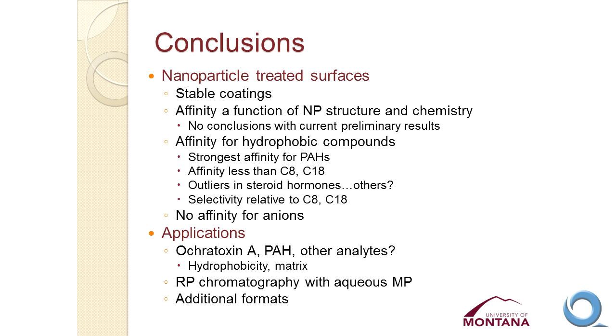All right, so to wrap up what we've done in 6 months, we coated several different surfaces with these nanoparticles, and we found that we get very nice stable coatings. We found the affinity is a function of the nanoparticle structure and chemistry, but we can't really tell you which structural factor is the most important, or talk about any kind of trends, because we don't have enough data. We know that we get strong affinity for hydrophobic compounds, very strong affinity for the polynuclear aromatic hydrocarbons, but that is less than that for C8 or C18. That's a disadvantage in terms of the amount that you could extract, but it's an advantage in terms of the ability to desorb and recover the PAHs.